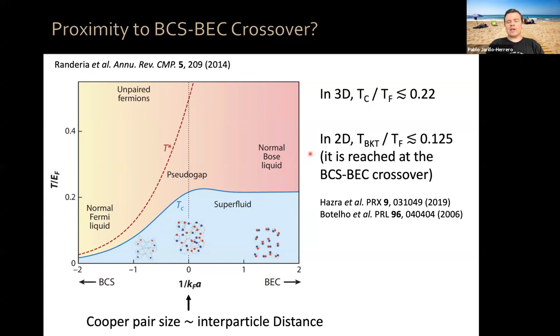But in order to check this, what we can do is apply a displacement field so that we hybridize and we get rid of the massless component of the electronic structure, and then we can see a sort of continuity. We can see that when we're measuring our effective mass values, you will see them in the next slide, they correspond to heavy electrons.